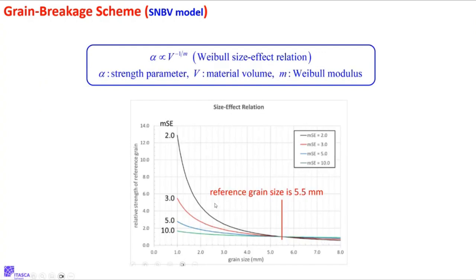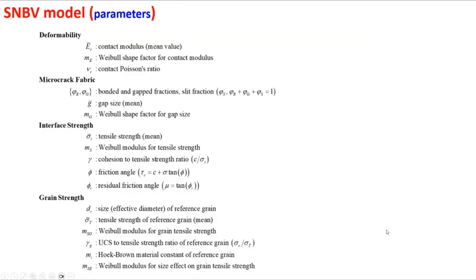And so this is saying, look at the green curve: the grain size gets big, the strength gets small. The grain size gets smaller, the strength gets bigger. And there's a parameter that controls which curve you're going to get. Okay. So in the end, then, this model, kind of crazy. It has 18 parameters. Count them up. So for the deformability, remember, contact modulus, contact Poisson ratio, Weibull shape factor.